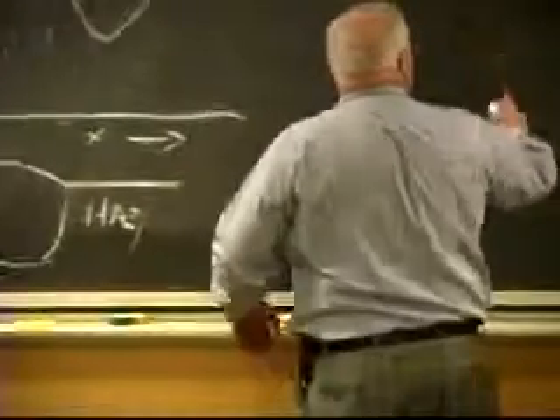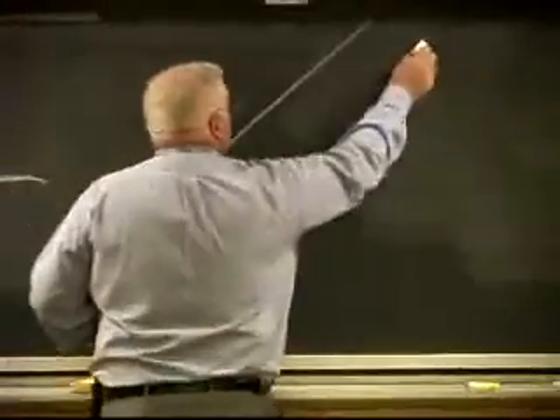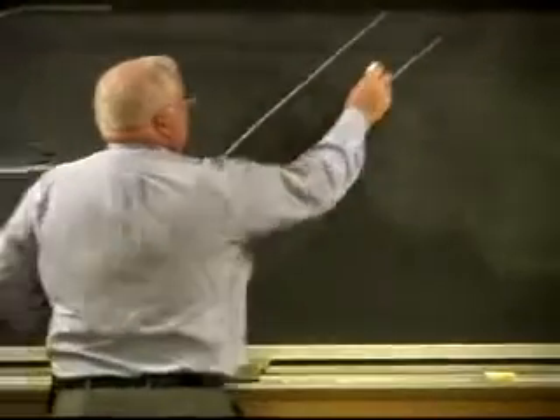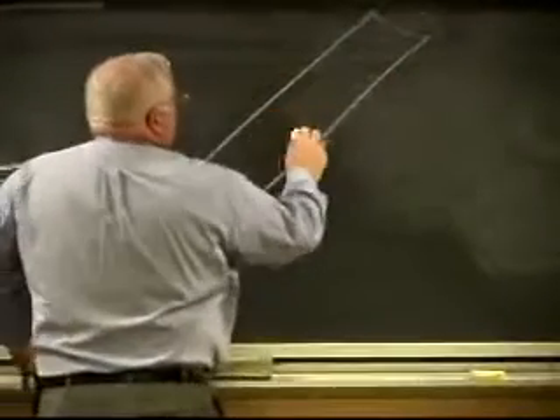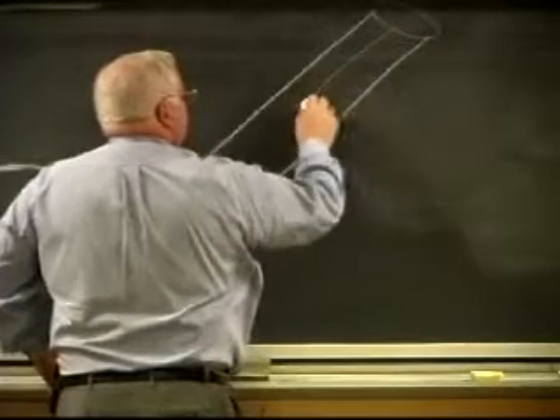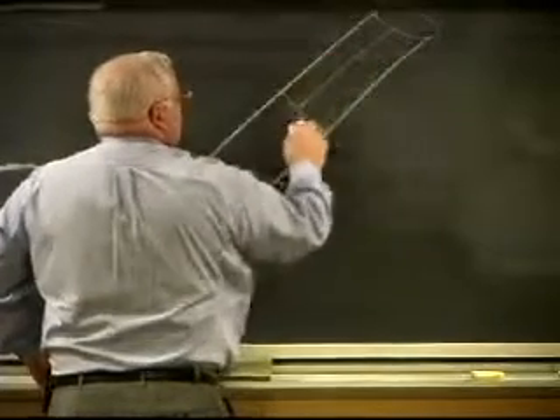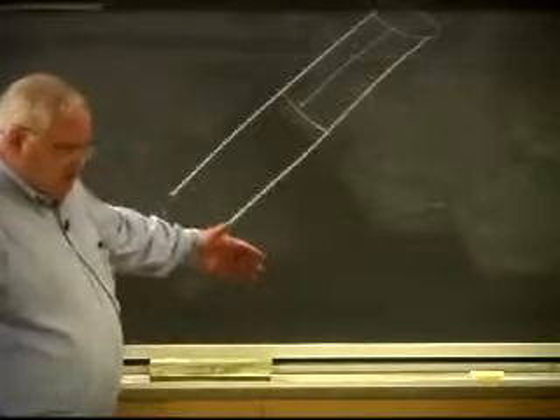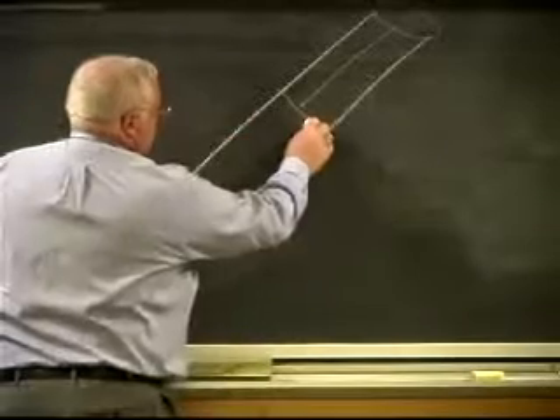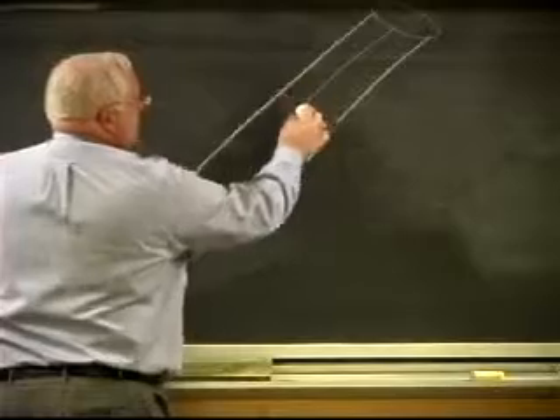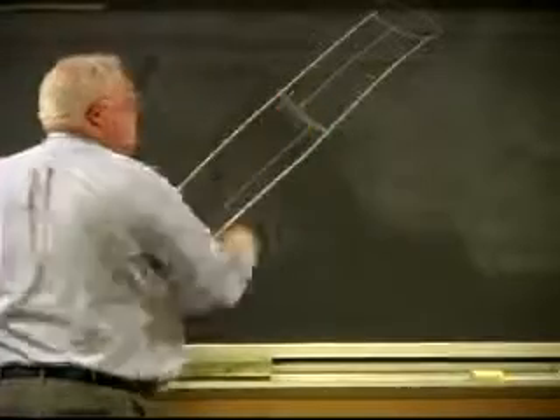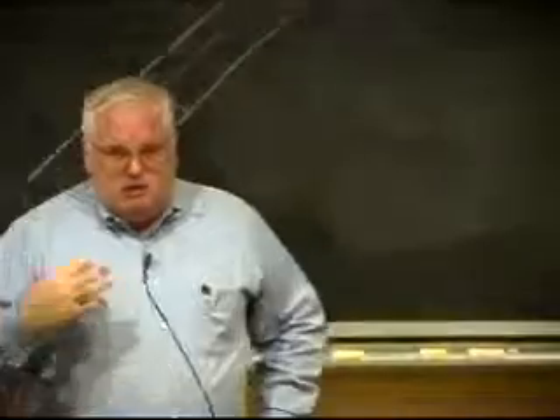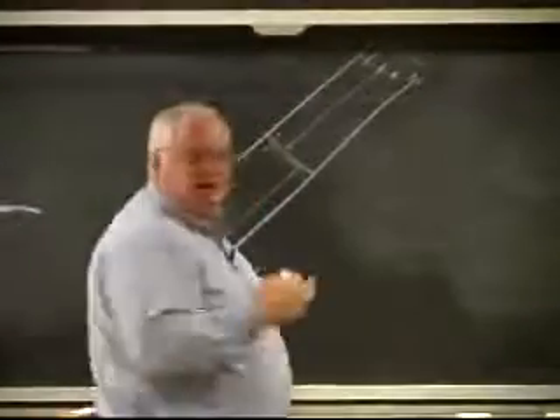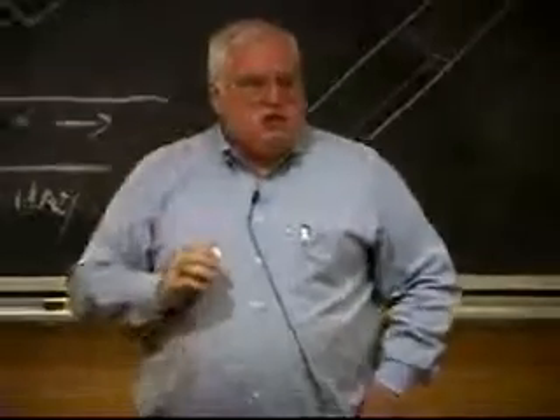Anyway, what had happened is they had these 4 long tubes, about 50 meters apiece, that basically hold up the main structure, and they had originally designed it so the welds were going to be between the plates of aluminum. This was like 6 or 10 feet in diameter, I can't remember, I never saw the real thing, but they had some longitudinal welds between the plates, and then they had a circumferential weld, and they beefed up these circumferential welds because this was a heat-treated aluminum alloy, and they knew the welds only had about half the strength they were supposed to have. So they designed the welds with extra support, gussets and things, to transfer the load across the weak weld.